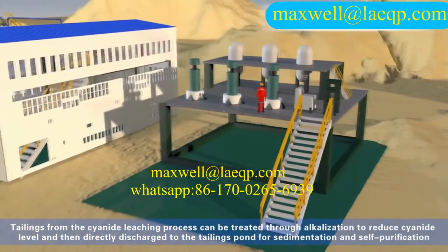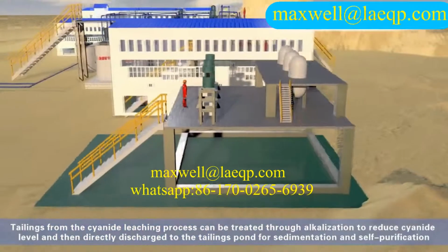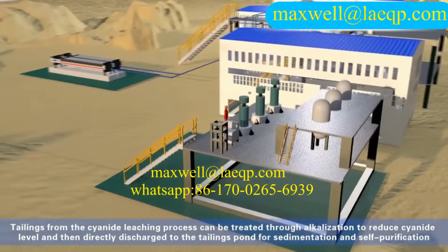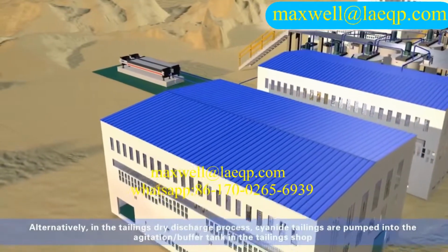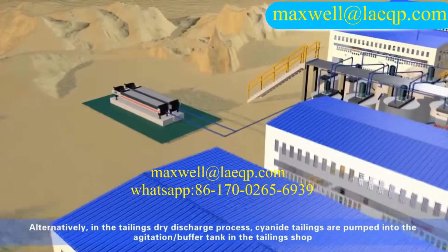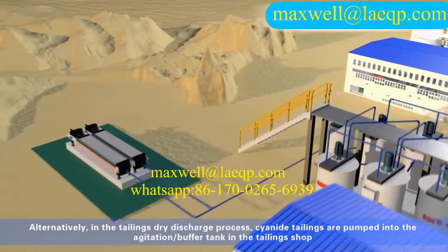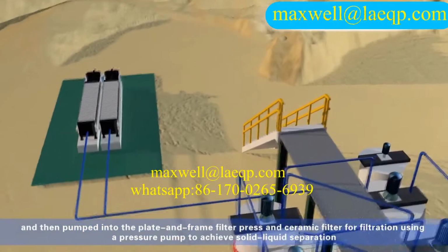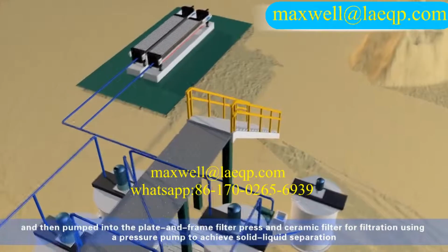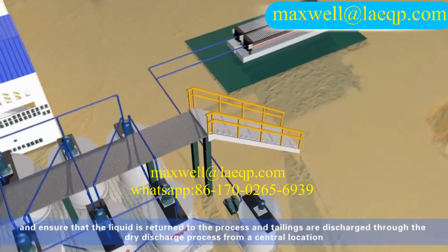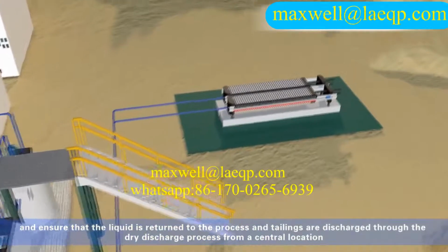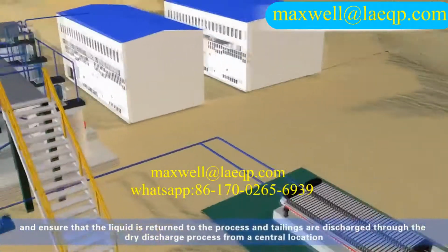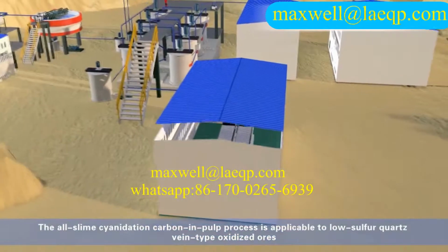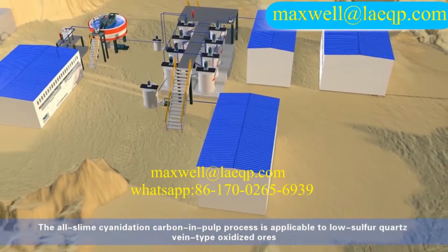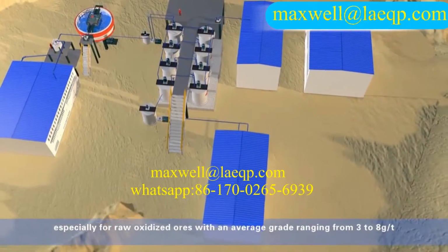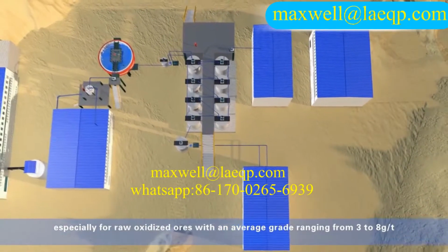Tailings from the cyanide leaching process can be treated through alkalization to reduce cyanide level and then directly discharged to the tailings pond for sedimentation and self-purification. Alternatively, in the tailings dry discharge process, cyanide tailings are pumped into the agitation buffer tank in the tailings shop and then pumped into the plate and frame filter press and ceramic filter for filtration using a pressure pump to achieve solid-liquid separation and ensure that the liquid is returned to the process and tailings are discharged through the dry discharge process from a central location. The all-slime cyanidation carbon in pulp process is applicable to low-sulfur quartz vein-type oxidized ores, especially for raw oxidized ores, with an average grade ranging from 3 to 8 grams per ton.